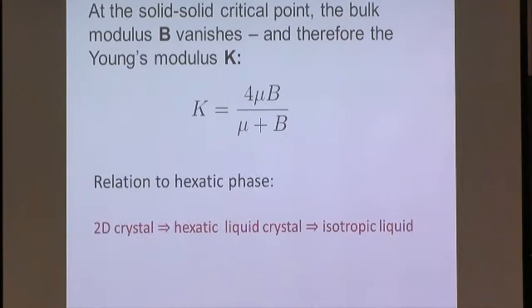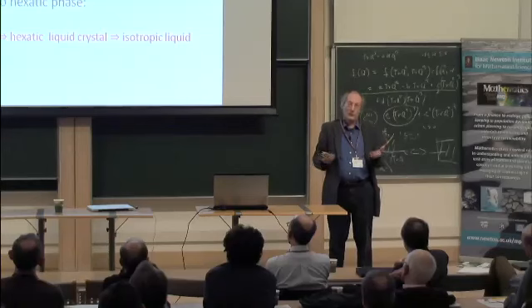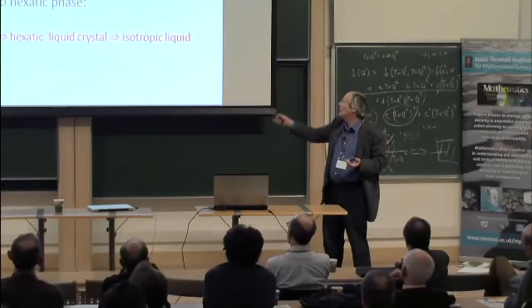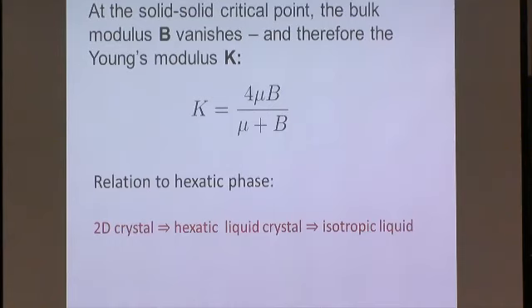Now, why is that important? Because there's a relation between the possible vanishing of this object K and the existence of a hexatic phase. And a hexatic phase is a phase that has no long-range translational order, but it has quasi-long-range orientational order, in the sense that the memory of the direction between two bonds between particles, disks in this case, is correlated over very large distances, and that correlation decays algebraically rather than exponentially.